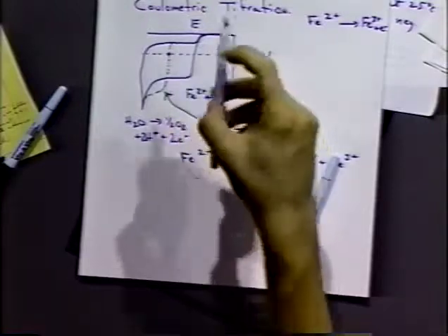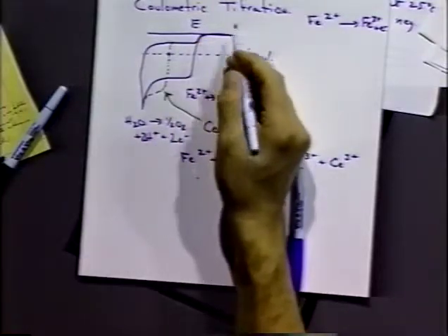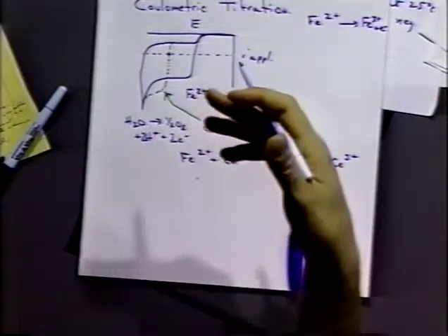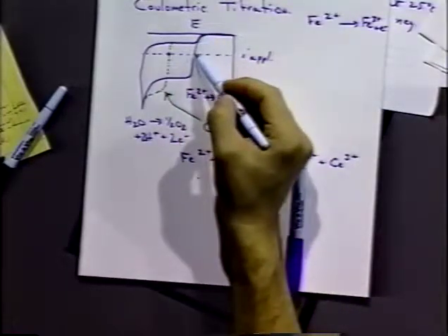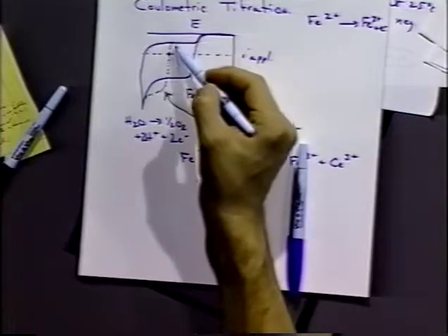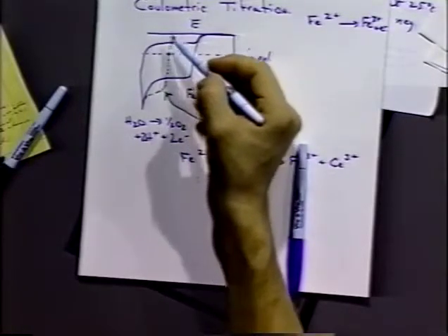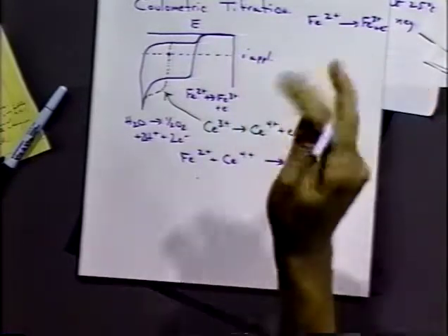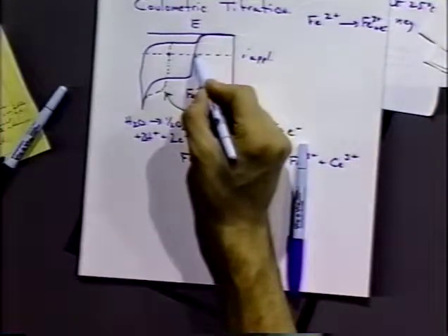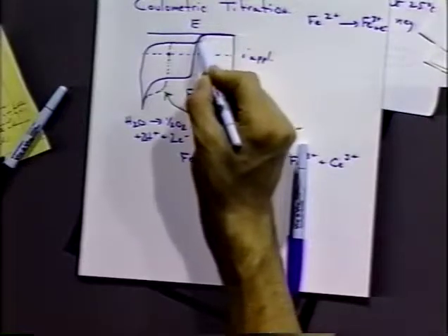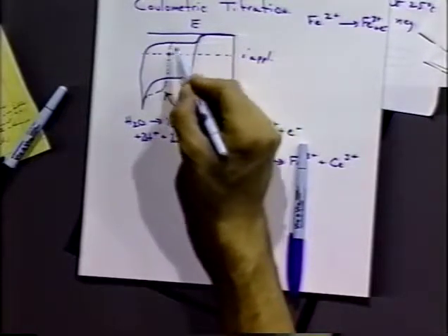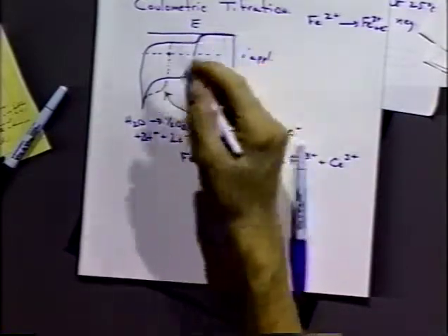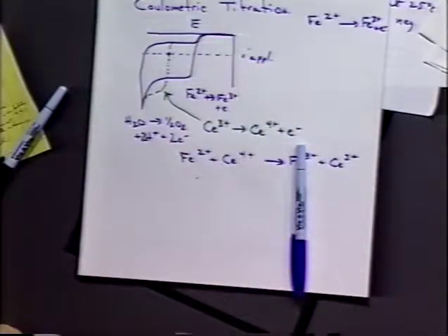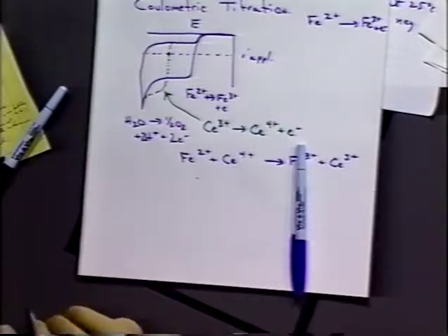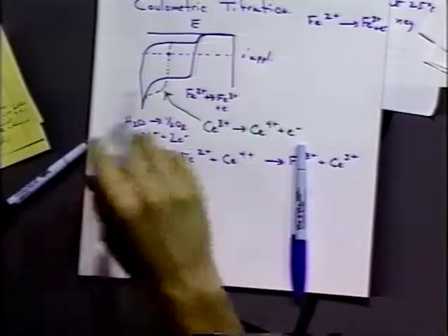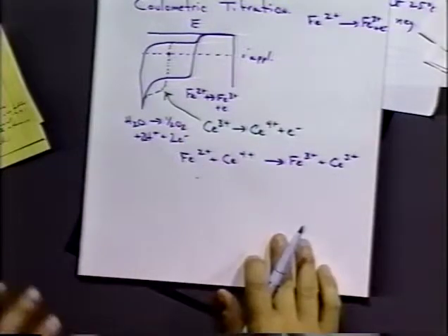As soon as we got to the point where iron 2 is all gone, there's no possibility for that equilibrium to be in place. And so the potential of the solution would shift to the point where the cerium 3-4 equilibrium is taking place. So by monitoring the solution potential, we could actually see, okay, we've shifted from this potential, which is going to slowly shift during the course of the titration, to this potential, which would be a very abrupt shift. And we could monitor that particular point. And that would be a good way to detect the end. Not the most precise way, though. Let's think about some better ways to do it, though.